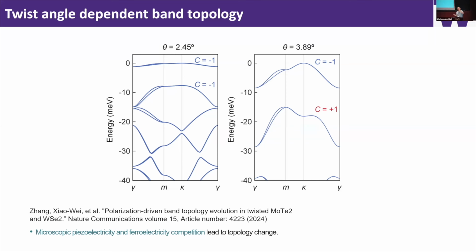And this competition depends on the twist angle. At a large twist angle, for example, the charge transfer dominates, which will give you one sign of Chern number. And when we go to small twist angle, the in-plane piezoelectric polarization actually dominates because lattice relaxation becomes stronger at small twist angles. So that gives you different signs.